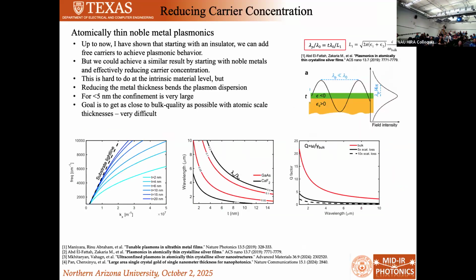But what if we went the opposite direction? What if there was a way to take charges away from metal? Well, that's actually pretty hard to do, but we got some clues from some of the previous work I was talking about and from one of the recent hot fields in plasmonics, which is plasmonics in atomically thin crystalline silver film. It turns out that when you start looking at plasmon modes in really, really thin films, you can get these bound modes that show pretty strong confinement in the mid-infrared. You have to reduce the thickness of your metal immensely to the point where you can treat it essentially like a 2D conductivity. And then you can support a mode that essentially exists on both sides of this film.